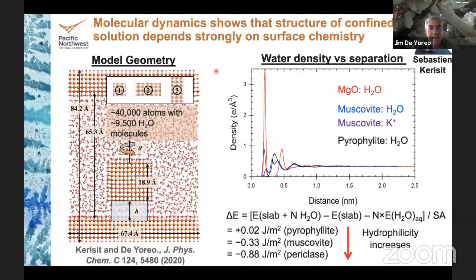So just to highlight some of these differences, I want to show you the results from molecular dynamics simulations from my collaborator, Sebastian Kiersit, of the effect of confining solution between surfaces on the solution structure and the control of surface chemistry on that. So this is the model geometry. Imagine bringing a nanoparticle down towards a surface, identical materials, identical faces, and we're simply going to look at the distribution of water between these surfaces as they approach one another as a function of distance and also as a function of orientation.